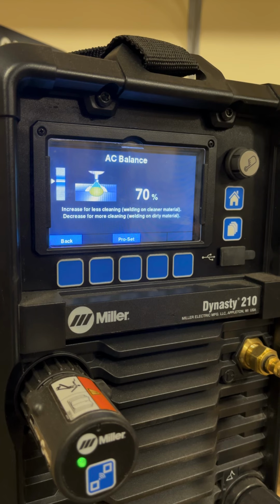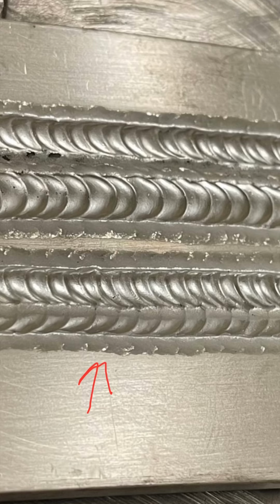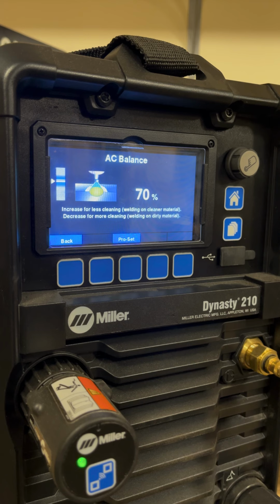Now you weld with that on aluminum because you need the DCEP side to provide what they call cathodic etching or cleaning action on the molten aluminum puddle and the surface of the aluminum in order to break up the surface oxide so your puddle's clean and it welds properly. So that's why if you don't have an AC TIG welder, you can't generally weld aluminum. So with AC balance, like I said, it's a ratio of EN to EP.